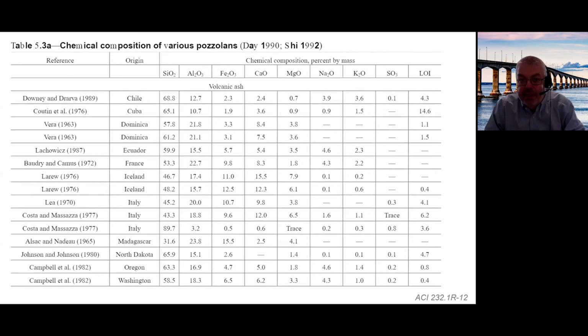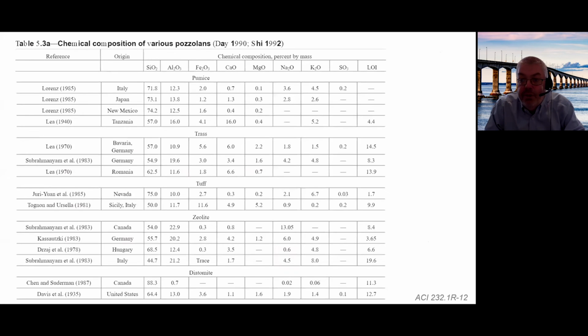And just stealing some tables here, which we're not going to spend any time on, this just shows the variation in chemical composition of some pozzolans. This is from published information, and you can see the silica, alumina, iron, and calcium content vary widely from one pozzolan to another. And the alkali content can be disturbingly high, as much as 5, 6, 7%. Usually not an issue with a natural pozzolan, because most of this alkali is tied up in crystalline phases and won't be available for ASR. But obviously we need test methods to determine whether that is the case or not.